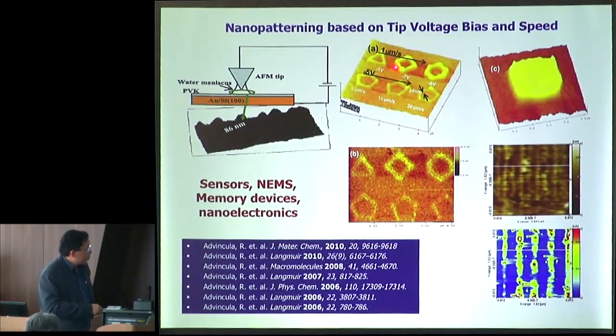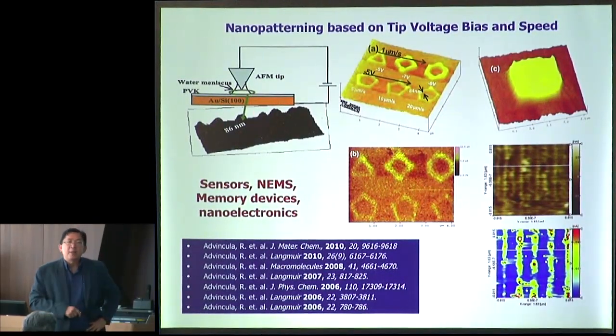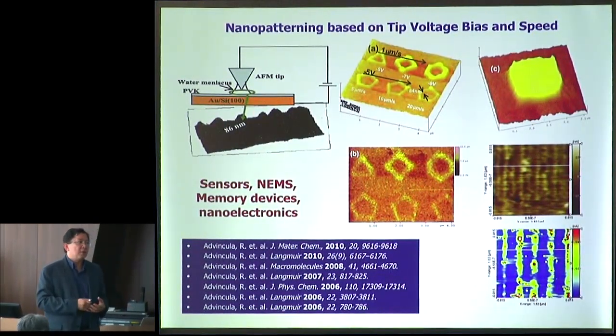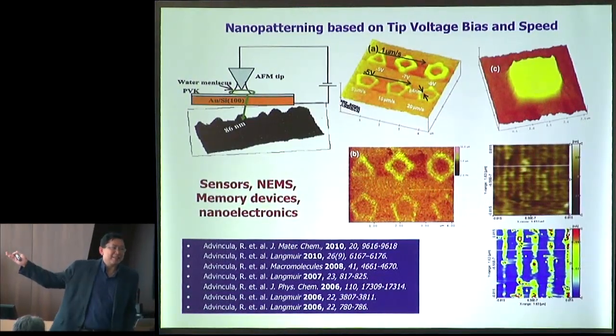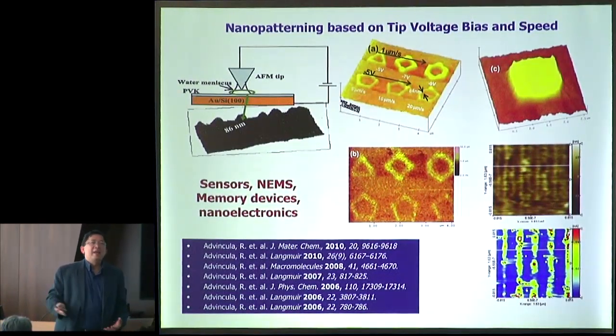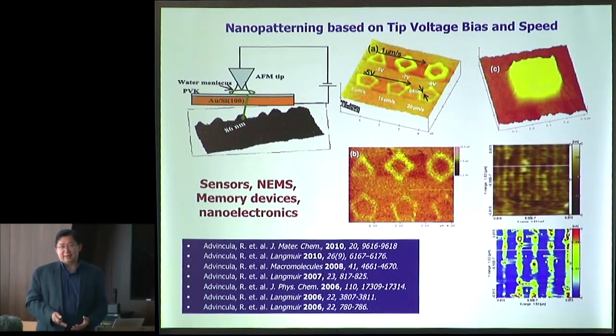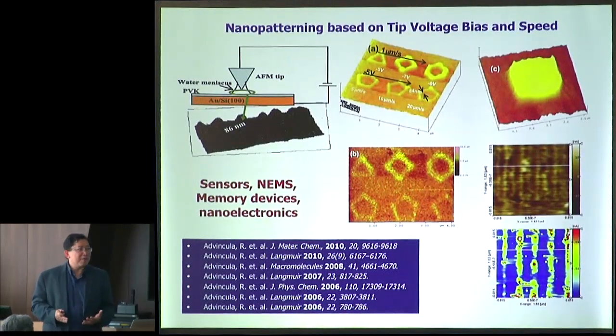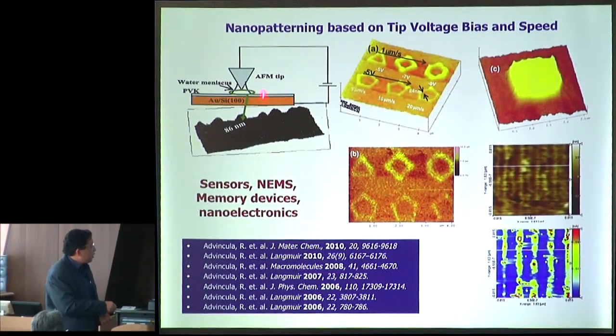So with this, we were able to build different structures, memory devices, different types of layer-by-layer films. And in fact, it was very fortunate when I was in Singapore, and always in Singapore you have weather like this, very hot, very humid. The experiment worked. The reason the experiment worked, we found out later, is that high humidity produces this wetting electrochemical bridge between the tip and the substrate.